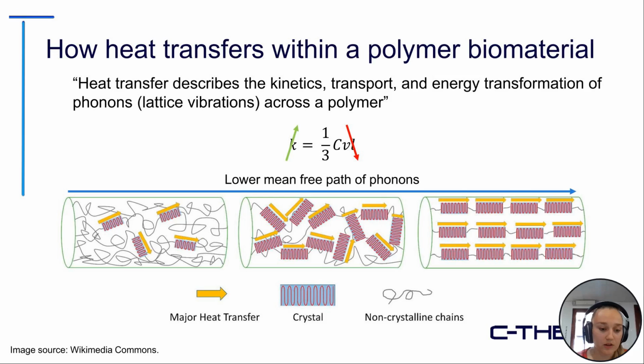When we're looking to quantify the overall performance of a polymer, you can take a look at the sample structure. For example, on the screen here, we see samples that are amorphous, and samples that are crystalline, and this has a very large impact on the thermal conductivity. As you can see on the screen with the arrows, as you decrease the mean free path or alternatively increase the organization, the thermal conductivity will actually increase.